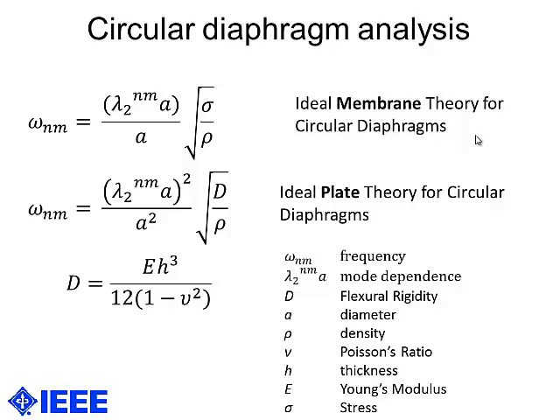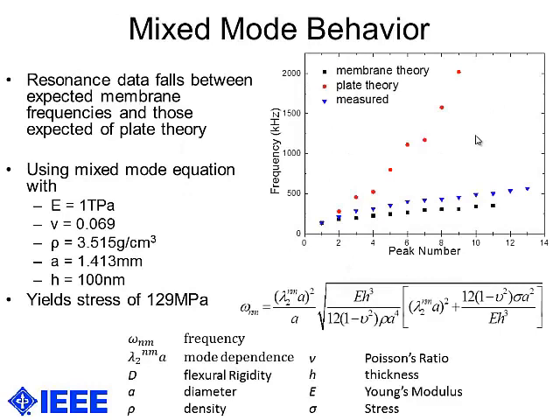Having compared the diaphragm to both of these equations, shown on the right here, we have the black at the bottom as the membrane equation, and the red going up rapidly is the plate equation. We found that our test results fell partly in between. Though they are similar to the membrane, they definitely don't fit our membrane equation.